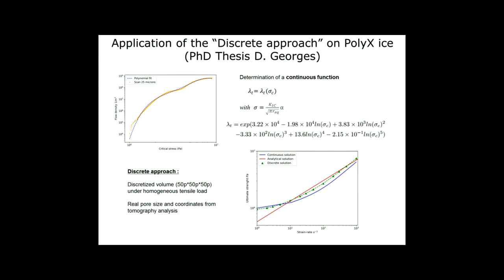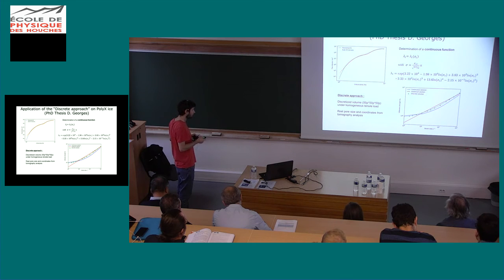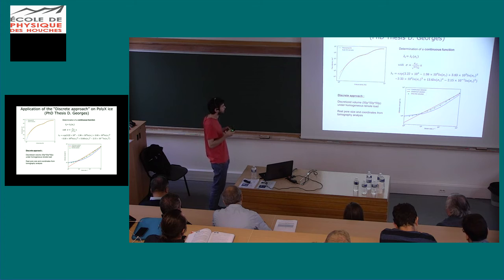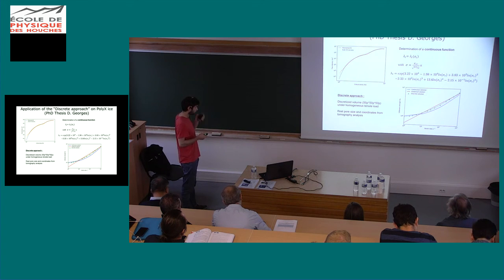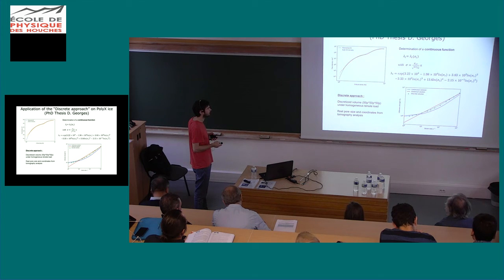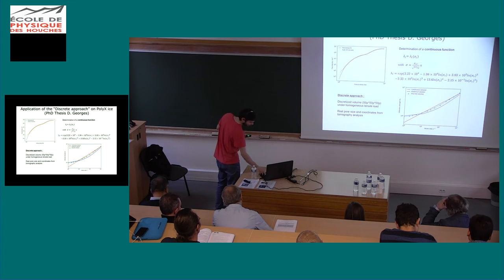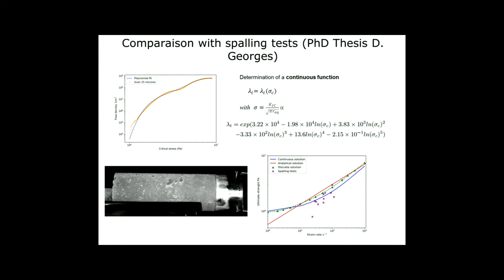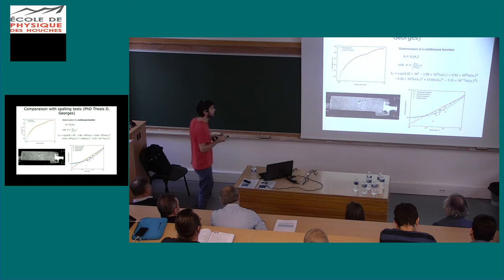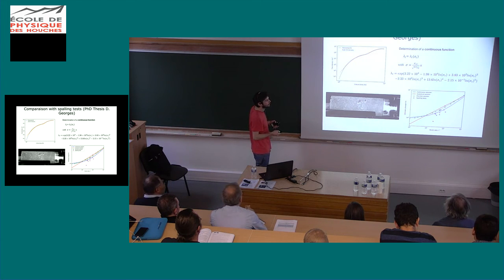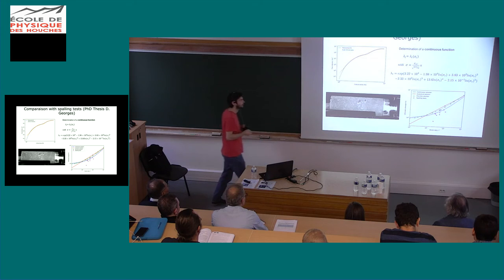Also, we performed the discrete approach. We loaded a discretized volume with a homogeneous tensile stress, by using the real pore size and the real pore coordinates of the center of mass. And here you can see the results in terms of ultimate strength for the discrete solution. You can see it's fitting the continuous solution almost perfectly. Also, we can add the spalling test results I showed you yesterday, and we can see that we have an excellent agreement between these test results and the continuous solutions we are using here.